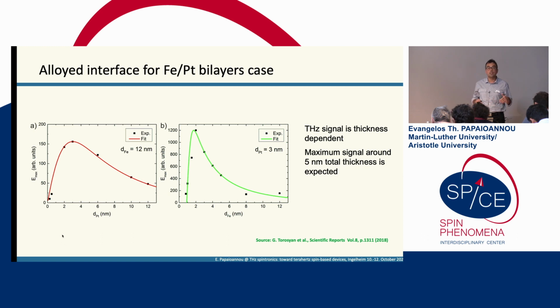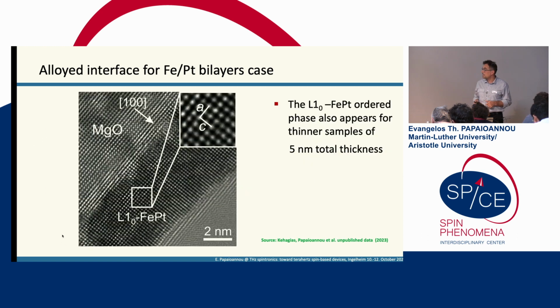So we now try to be at this peak. We try to induce the alloy at the 5 nanometer thickness. And this is what we did. This is really new data. So you see that in the total thickness of 5 nanometers, we again achieved, with our growth technique, to induce this L10 phase at the interface.